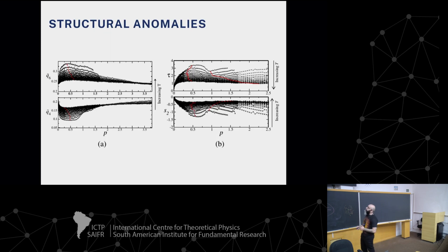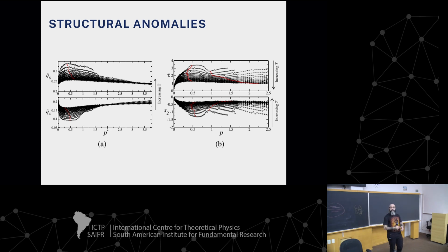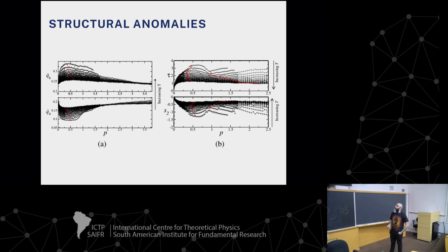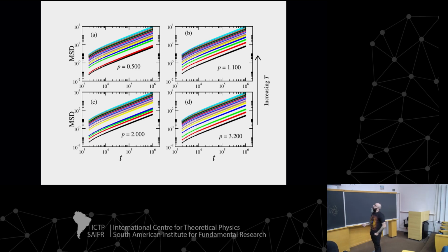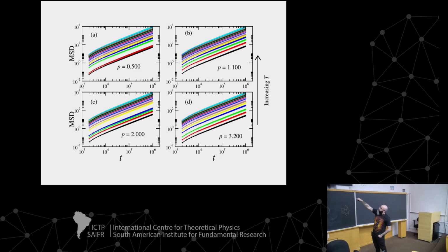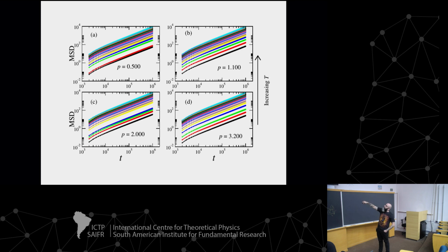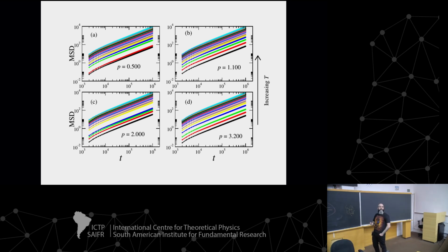But the system also showed the structural anomalies, as Marcia and Alain saw almost 20 years ago. And as I said, what was happening here on the left is the transition from the BCC phase with a low MSD to the fluid phase with a higher mobility. Here, HCP to fluid phase, you can see there is a huge gap, as expected for a first-order phase transition. Here we have a kind of second-order phase transition. There is no gap. As I heat up the system, you can see that my MSD starts to increase. In the amorphous to fluid phase, there is an indication that it is a second-order or continuous transition.